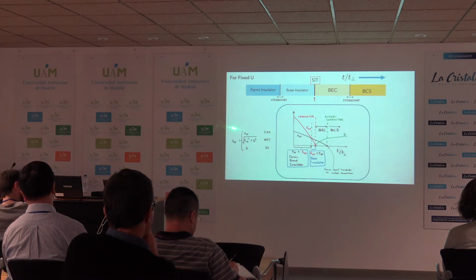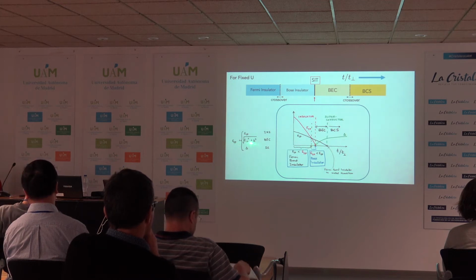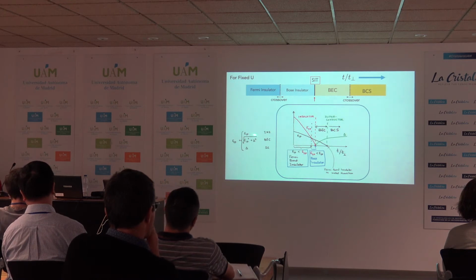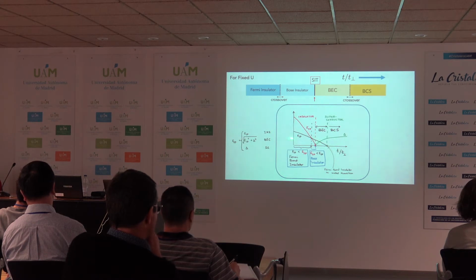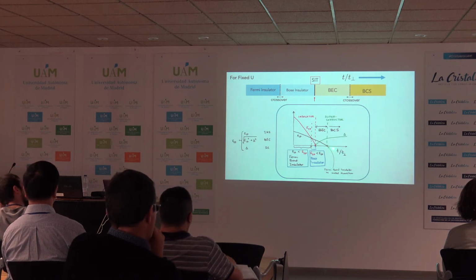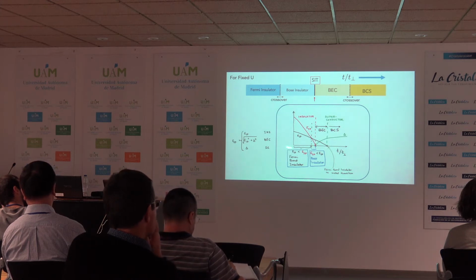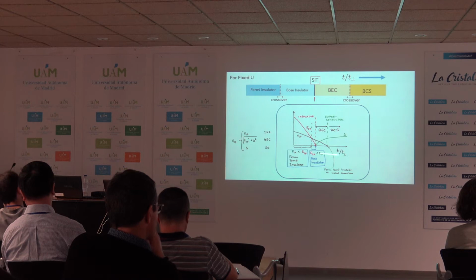On the Fermi insulating side, the single particle gap is just that one particle gap I showed you. It enters a BEC regime where the single particle gap is this geometric mean of the one particle gap in the spectrum and delta square. Delta square is now the gap in the superconductor. And then there is a point where this is the one particle gap that I had shown earlier that was closing at some value of the hopping, giving you a superconductor to metal transition at zero attraction. When that happens, this single particle gap goes to zero, and then of course the single particle gap just becomes delta. So that's what would happen in a BCS superconductor.